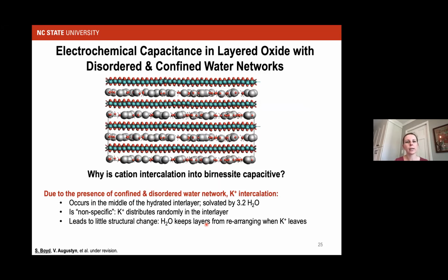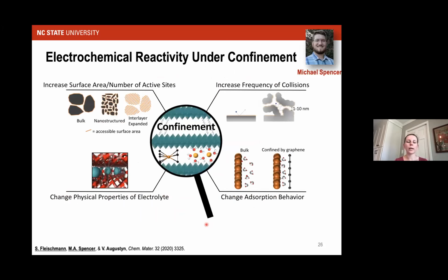Where we're going with our work is to take it up a step now that we know that these interlayers are essentially able to accommodate solvents and cations. We want to place in there more complex redox active species. The reason we want to do that goes back to the first couple of studies that I shared with you at the beginning of my talk, where having access to this inner surface, if you will, not only will increase your surface area and the number of times that your reactant molecule will collide with the electrode and potentially undergo charge transfer, but we know from these theoretical studies that whatever's going on under confinement will have changed physical properties compared to the bulk.